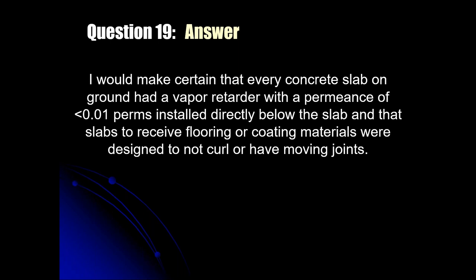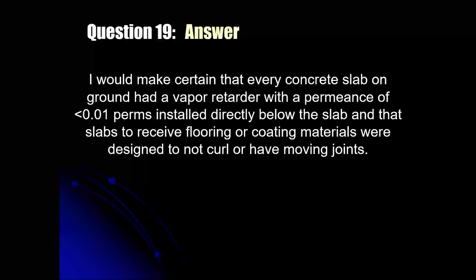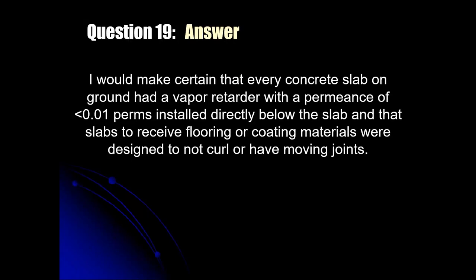For years and years, big box warehouses weren't putting vapor retarders under their slabs. That has changed significantly since ACI 302.1 and 302.2. We make the recommendation that if a moisture sensitive product is going to be stored directly on the slab surface, that big warehouse slab wants to have a vapor retarder directly under the concrete.